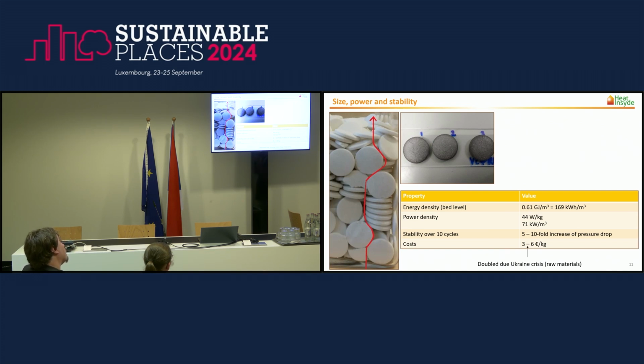If you want to go beyond that, you really have to find another material, and that's really dictated by nature. These are the power densities we get, in terms of per kilogram and per cubic meter. And then stability, for the moment, I define in terms of the increase in pressure drop we see over cycling. So we did cycles with the beds, and over 10 cycles we found a 5 to 10 fold increase